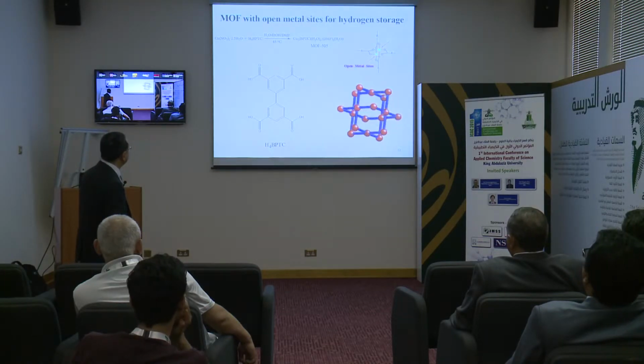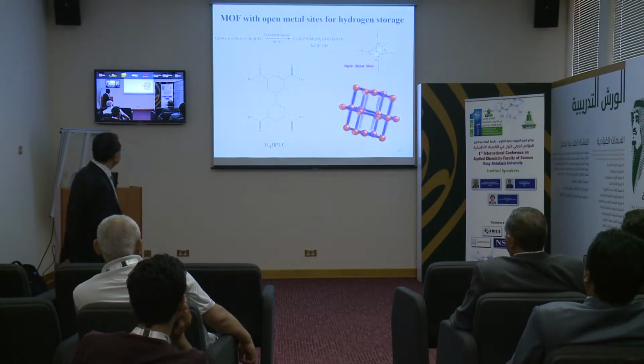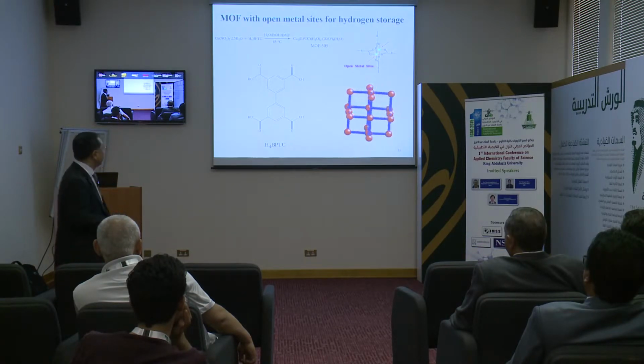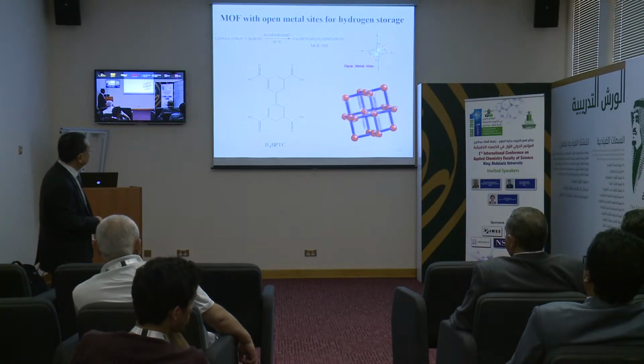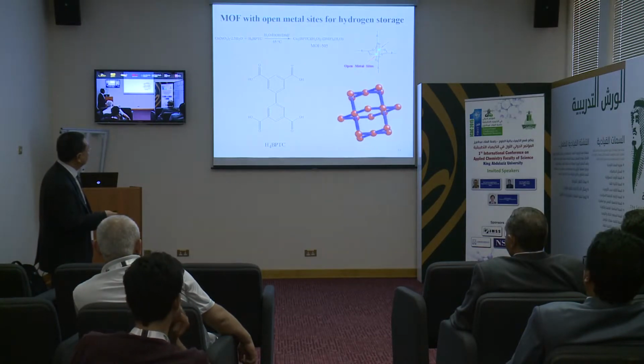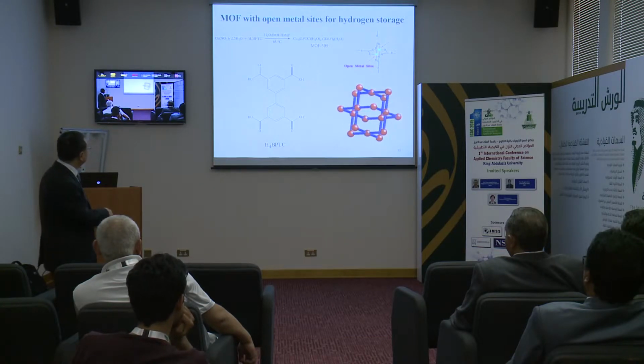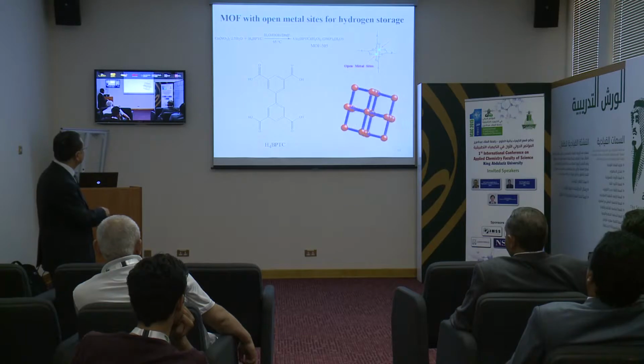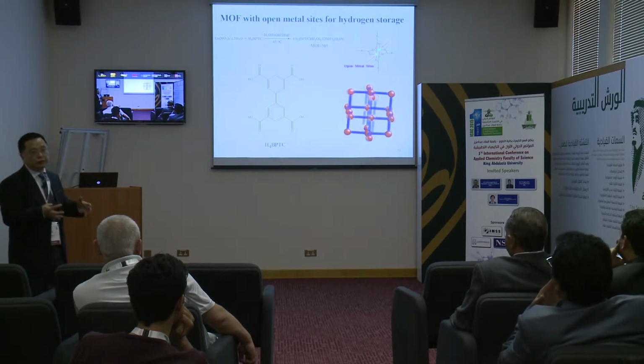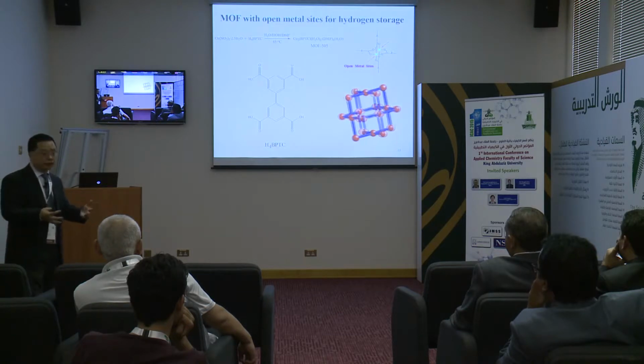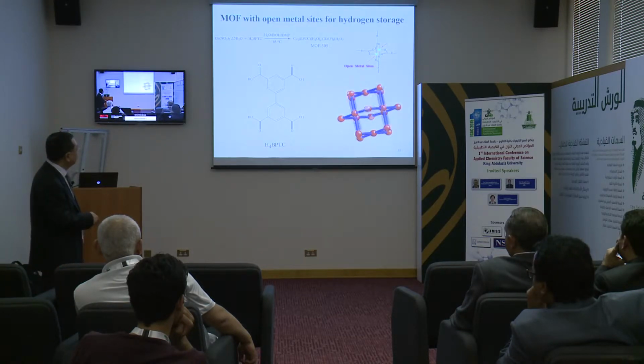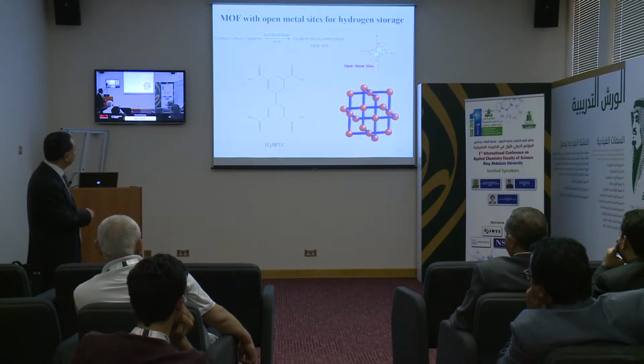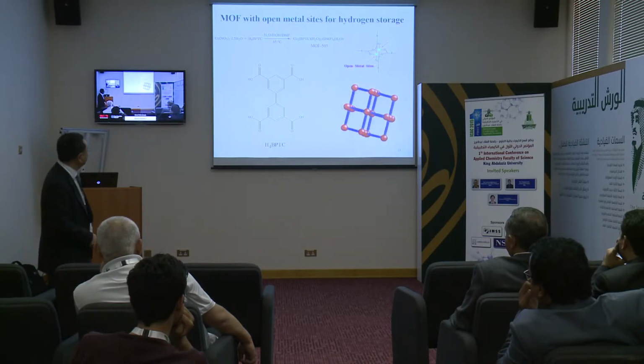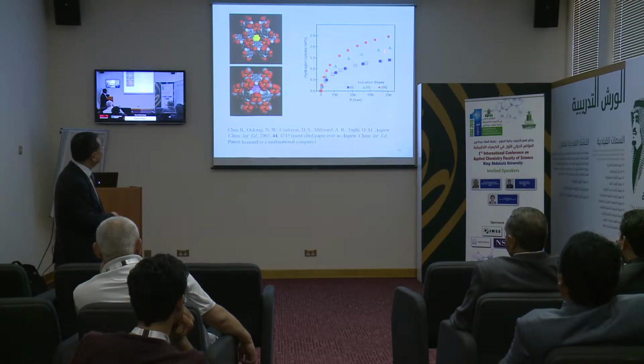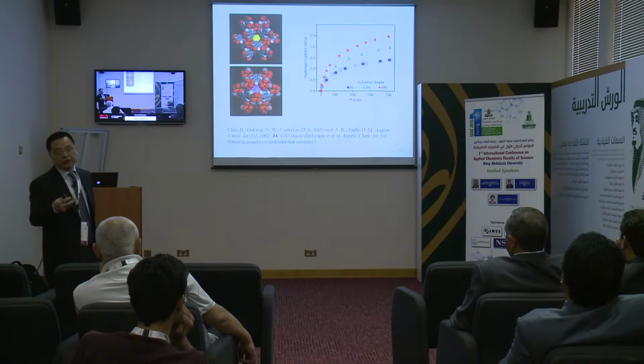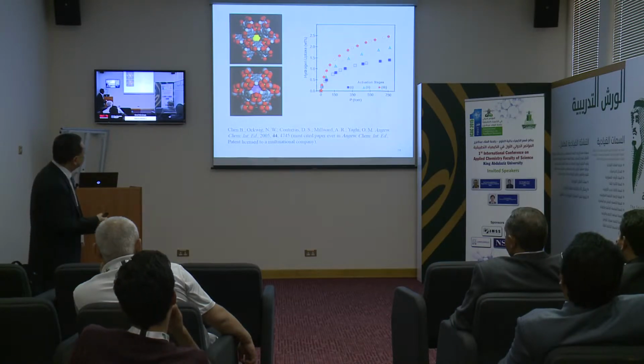To summarize, this is the first one from when I started my independent career. The work had some impact. Basically, one is the concept of the open metal site. Actually, this open metal site was generated several years ago. Secondly, this metal dicarboxylate unit turned out to be a very useful building block for the construction of metal organic frameworks. And of course, the structure is kind of predictable. This is a square planar, and this is another square planar to have a niobium oxide structure. So we realized that when we remove the solvent molecule to have an unsaturated metal site, the uptake of gas absorption is significantly enhanced.